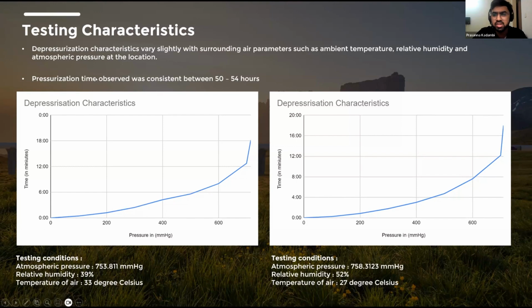The pressurization time, once the vacuum pressure has been reached up to this point, normally takes, at any part of the day, around 50 to 54 hours in order to pressurize the entire tube to equal pressure on both sides, on the inside and on the outside. And this is something which does not vary with time or with any of the parameters. It is very consistent between 50 to 54 hours.